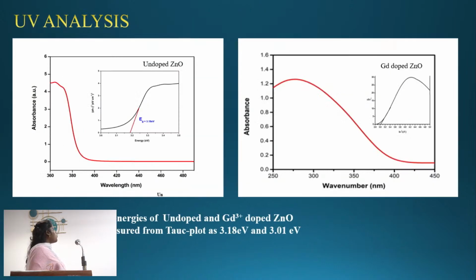The next one is UV analysis. These are my UV analysis results. The first one is undoped ZnO and the second one is gadolinium-doped ZnO. The absorption peaks are at 375 for undoped and 325 for gadolinium-doped ZnO. The band gap energy is calculated from the Tauc plot as 3.18 electron volt for undoped and 3.01 electron volt for gadolinium-doped.